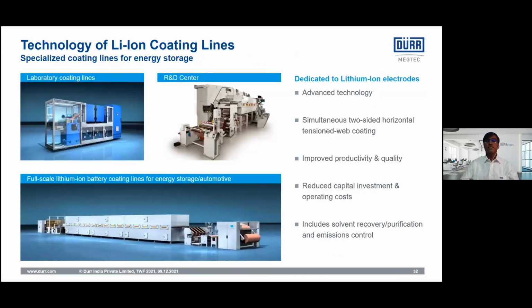Dürr builds lithium ion coating lines for R&D laboratory and full-scale production with a foil width ranging from 250 mm to 700 millimeters, and speeds in the range of 0.5 meters per minute up to 80 meters per minute. This offers a complete capacity of 0.1 megawatt hour per annum up to 1000 megawatt hour per annum.